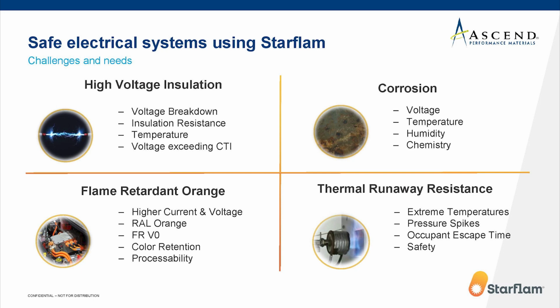This had to be considered where extreme temperature rises and pressure spikes are observed, and there's the need to delay the runaway spreading the fire as long as possible to increase escape time. Our first development can last about 2 minutes in this test, but we needed a more specialized design for longer delay times. And Kai Becker will cover in the second half a system that can last up to 15 minutes.